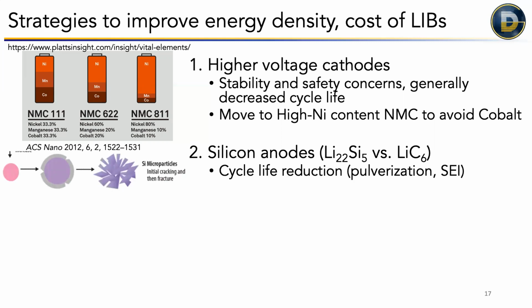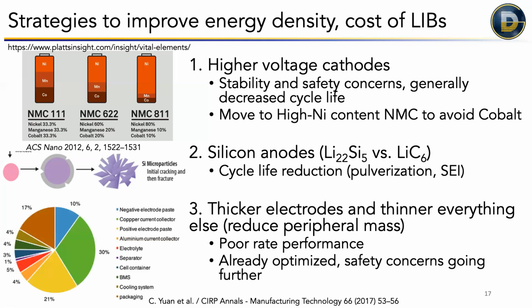Now we're trying to mix in some silicon into the graphite, because you can put a lot more lithium into silicon. The problem is when you put so much in, it expands and then pulverizes itself. So it can't withstand the expansion, but that is definitely something that's happening right now. And then you can do some things at the system level, go thicker electrodes and thinner everything else, so that all of your mass and space is the stuff where you're actually storing energy. But that leads to poor rate performance, because those lithium ions can't get through that really thick electrode. And a lot of the other things like the separator are already pretty optimized. And if you try to go further, you risk safety concerns.